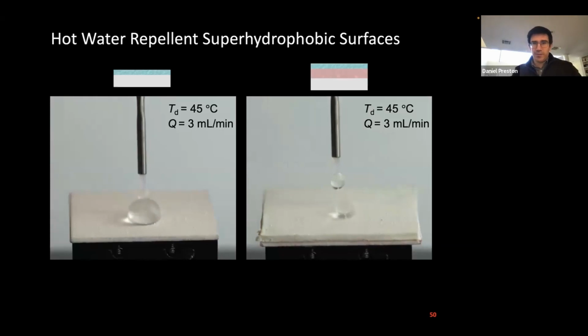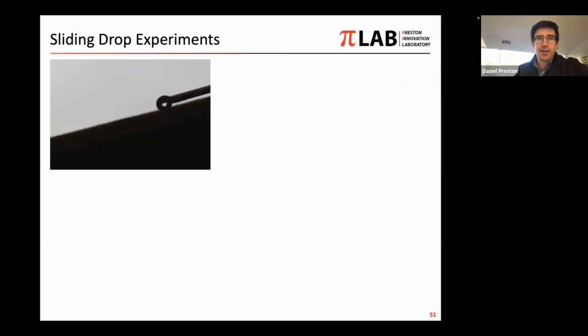And so again, here's the video we looked at earlier. We see clearly that the performance is enhanced at these elevated temperatures by introducing the insulating layer. To be more quantitative, we did some sliding drop experiments. These are inspired by and quite similar to the ones in the prior CAREER paper.